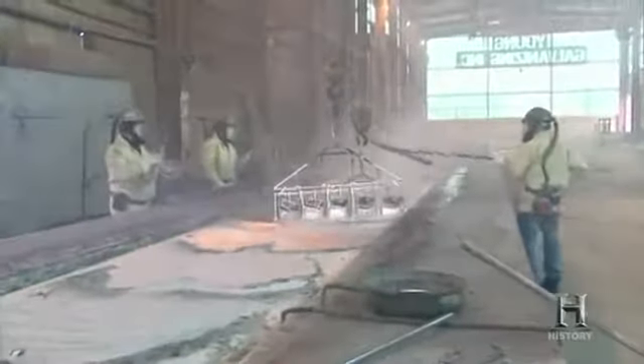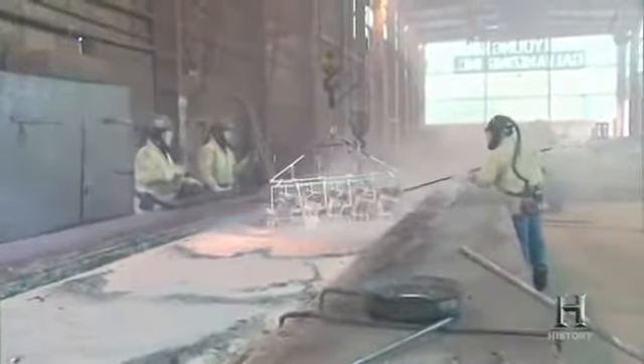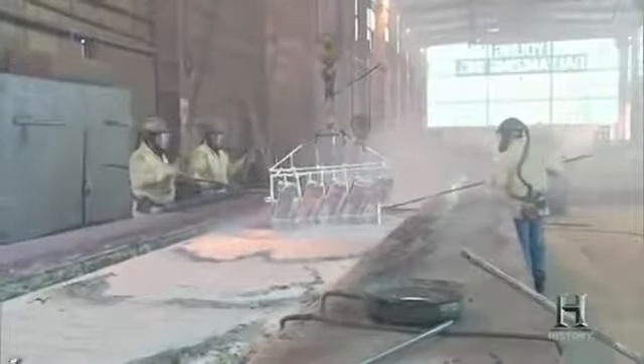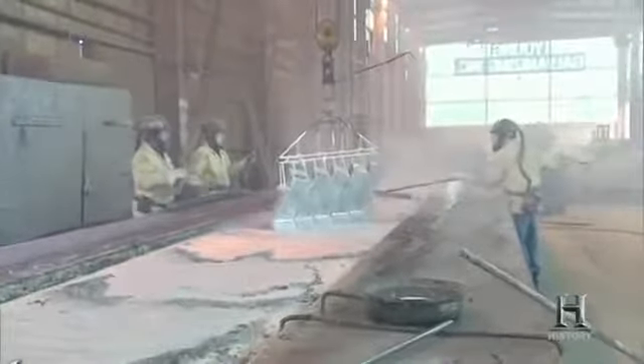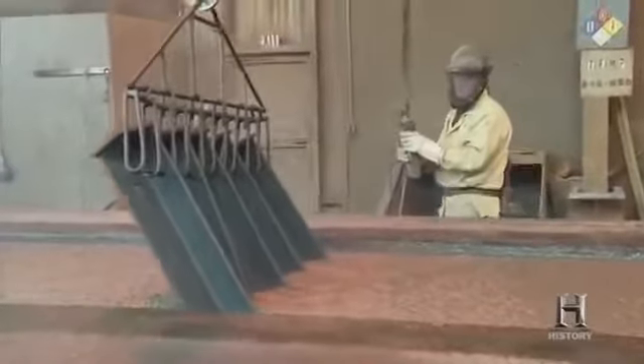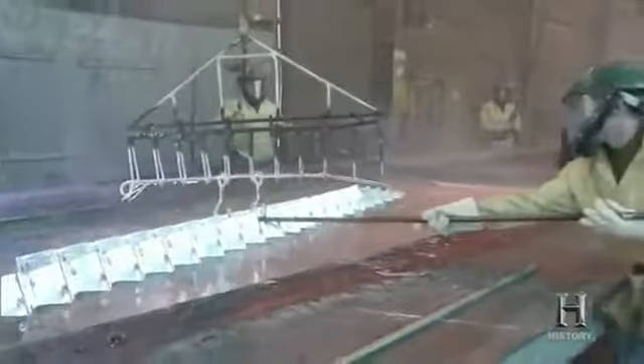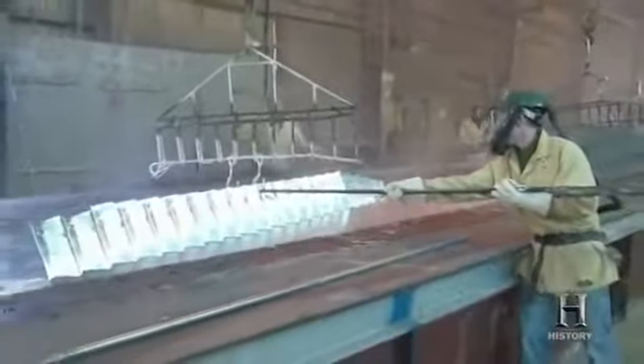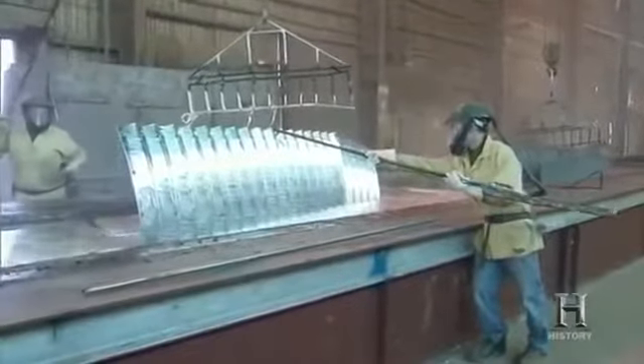Here at Young Galvanizing near Pittsburgh, the galvanizing kettle is 48 feet long, 5 feet wide, and 8 feet deep. Big enough to submerge the largest pieces of steel. The steel is immersed in zinc until it reaches a bath temperature of 840 degrees Fahrenheit. The zinc and steel actually form a metallurgical bond, an alloy that will resist rust and corrosion for many years to come. Zinc has thus fulfilled its role as the great protector.